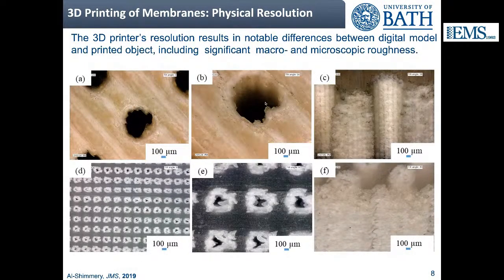Finally, a key thing about the limitations of the physical resolution of the printer is that you get quite a lot of macro and microscopic roughness. You see it in these images here. Rather than a perfect circle, you're getting some roughness. And in the image on the top right, image C, this is a cross-section of the pore in B, and you can see that throughout the length of the pore, you have roughness. Now, this could be a bad thing for a certain application, but you could also try to use this to your advantage in a different application. But you need to be aware that there's an element of roughness coming from the limitations of the printer's resolution.